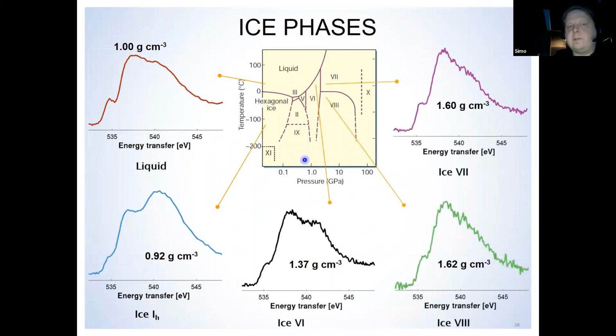So these are the fingerprints that were considered at that time. And then we go to these ice phases, ice 6. All of these, I should mention, have a fully bonded hydrogen network. Ice 6 has already a quite diminished post-edge and a slow starting increase of the pre-edge structure. And when you go to ice 7 and ice 8, they have very similar density and otherwise very similar structure, except for the proton disorder.